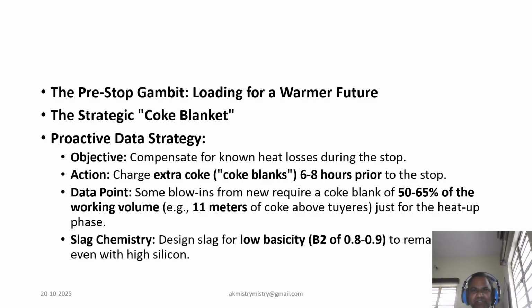To give you a sense of the scale of the heat requirement, some full furnace startups need a coke blanket representing 50 to 65% of the entire working volume. That can be a column of coke 11 meters high above the tuyeres just for the heat phase. And alongside this, they engineer the slag chemistry for a low basicity, ensuring it remains fluid even with the punishingly high silicon levels. It's all about preparing for the worst.